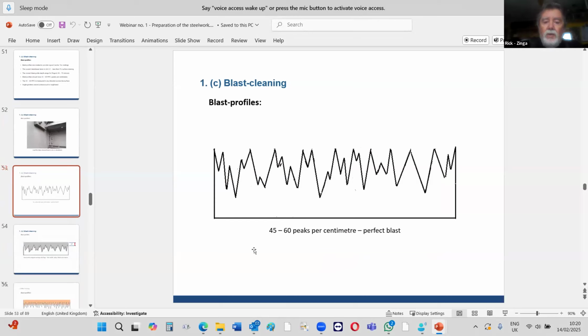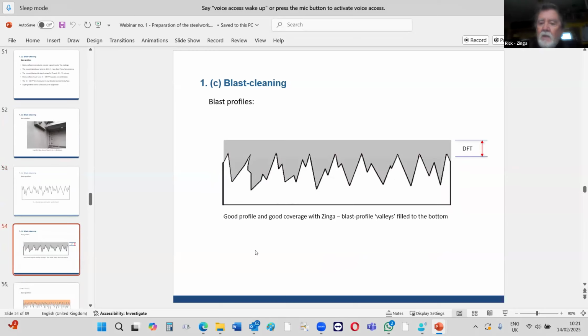So this is how it looks. So now you can see what I'm speaking about with all the peaks. So that's 45 to 60 per centimeter, and that's a perfect blast. And just remember, when you're measuring DFT, if you're using an electronic gauge, you're always measuring from the blast peaks. Many guys used to think that you measure from the valleys at the bottom. We said, no, because that's inside the metal. You don't see that. What you're measuring is above the surface of the metal. That's your dry film thickness.